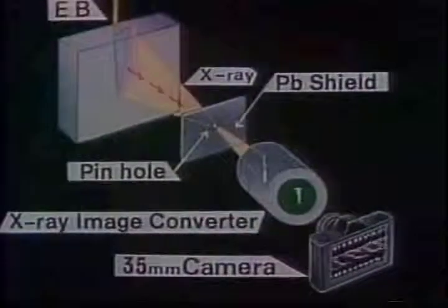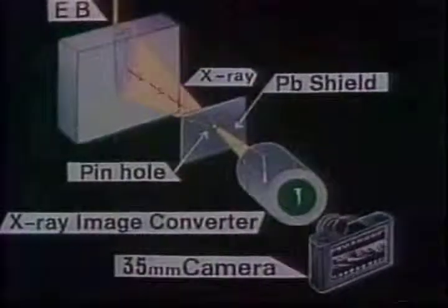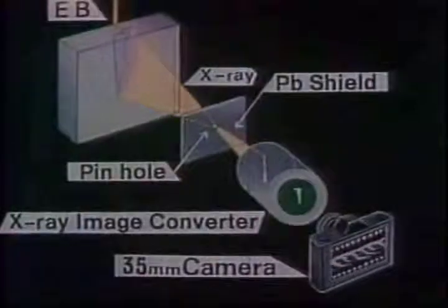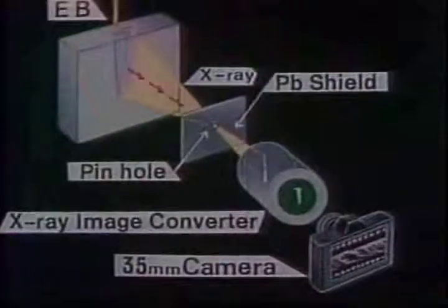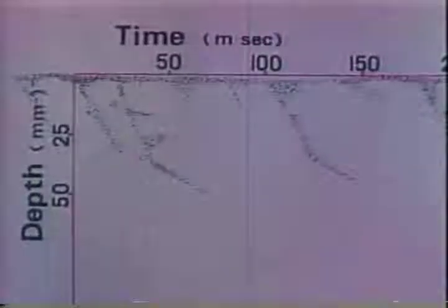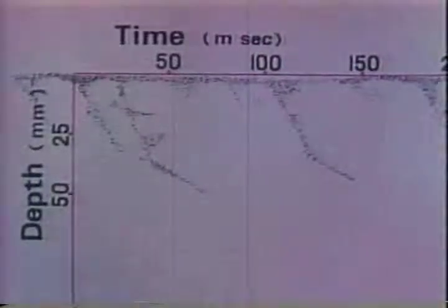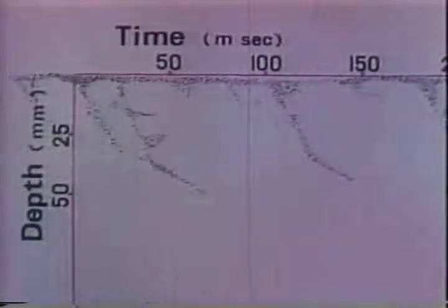In order to observe these phenomena more clearly, the streak photograph method will be very useful. When the film runs continually to the left and the bright point moves downward, the image of the oblique bright line, like this, is recorded on the film. This is the principle of the streak method. This is an example of an actual streak photograph, from which the speed at which the beam interacting point is moving is estimated to be several meters per second.